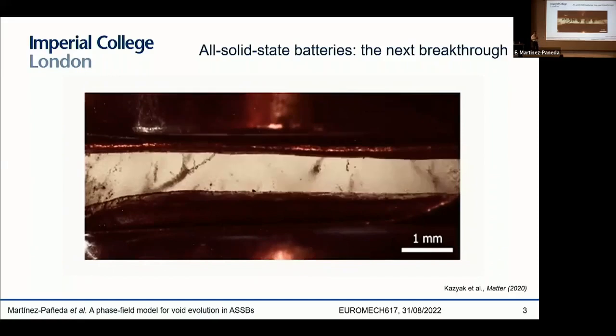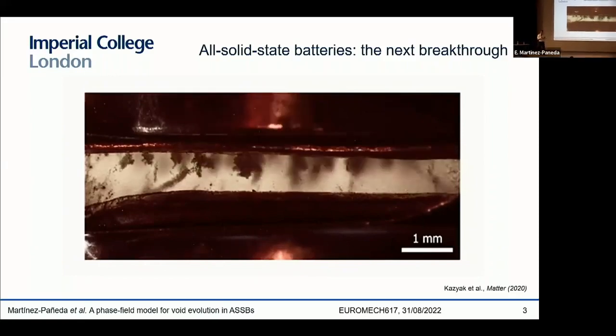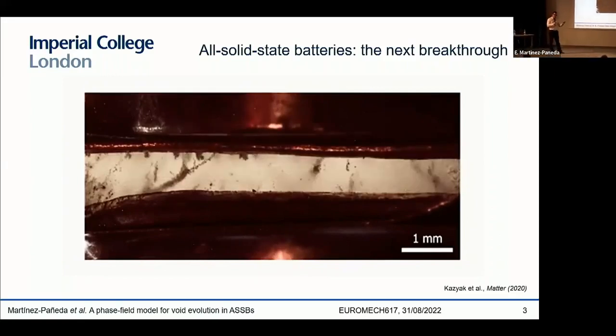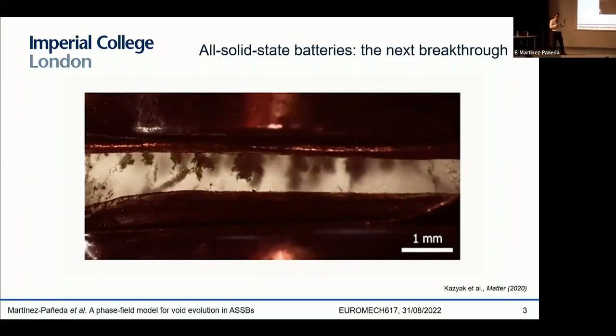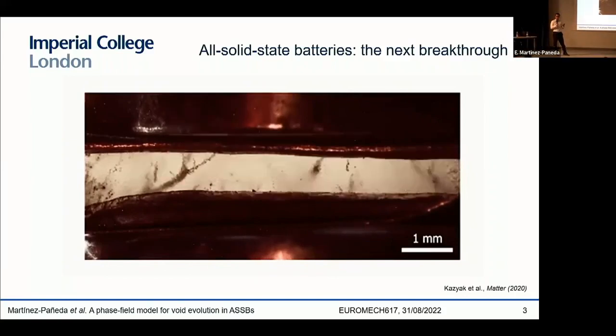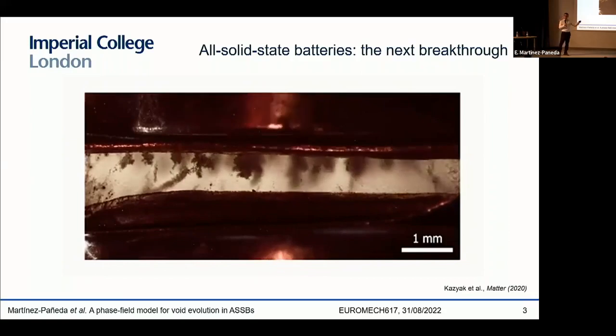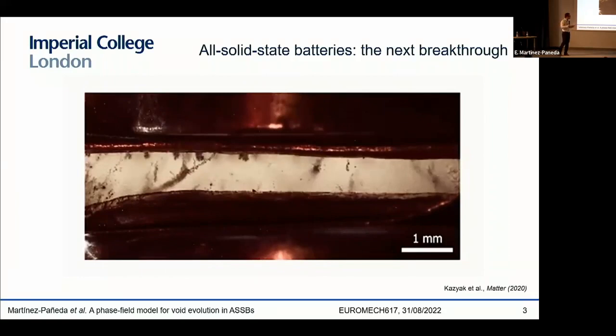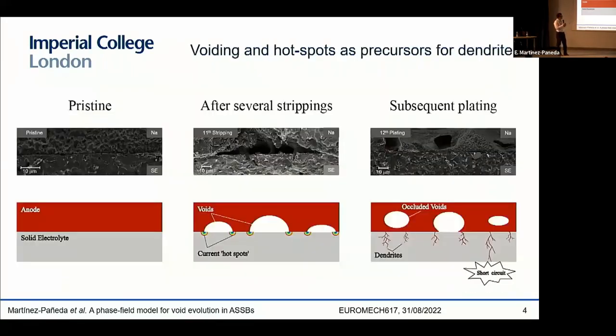So we thought that in our first attempt to come up with these modeling efforts, we should put the focus on trying to predict and understand under which conditions those dendrites nucleate. And what we know from experimental observations is that the formation of those dendrites is related to the evolution of voids in the lithium metal anode and the associated local current hotspots in the electrolyte. So let me elaborate on that a little bit with these nice microscopy images from Peter Bruce's group in Oxford and some sketches that I've done below.